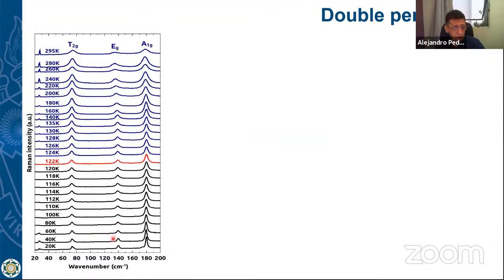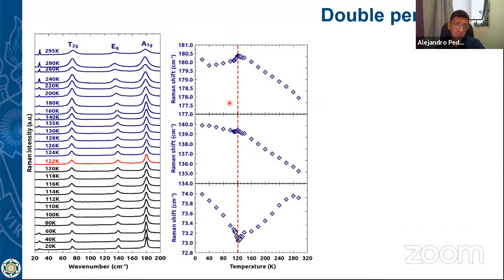If we do some Raman spectroscopy, we can start Raman spectroscopy as a function of the temperature. The theory reproduces quite well the experimental results. And if you take a first look at the spectra, it looks like nothing happens. But taking the position of the Raman peak as a function of the temperature, we are using a very common unit for vibration spectroscopy, which is called wave number, the inverse of the centimeter. But it is proportional to energy. So higher wave numbers are higher energy. It's a traditional unit of the field.